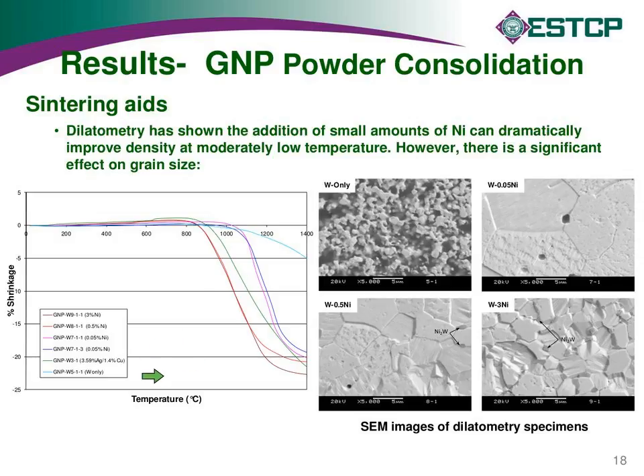Now this slide, so the light blue line is the sintering shrinkage that you see with temperature for the tungsten only. You can see that we needed on the order of 20+% linear shrinkage for the green densities that we worked with. The tungsten only was requiring very, very high temperatures for sintering shrinkage, at which point, because these powders are agglomerates, they would grow to the agglomerate size, so we'd get a lot of coarsening of the tungsten. So we couldn't really maintain the tungsten particle size at density. So we knew we needed to add some type of a sintering aid.